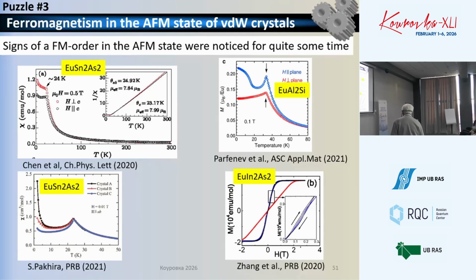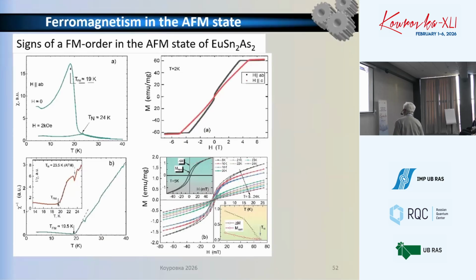So what I want to say is that in all the layered antiferromagnetic materials, you may find signatures of ferromagnetism. To explore this issue, we took a single crystal, and we didn't apply a magnetic field like this, and we see a huge manifestation of ferromagnetic behavior. Of course, when you apply 0.2 Tesla, you immediately wash it out and get what is reported in many papers in the literature. Furthermore, we took precise measurements of the magnetization curve and found, in the tiny vicinity of zero magnetic field, ferromagnetic type hysteresis. It saturates and vanishes. It saturates fully in fields which are much less than the saturation field of the antiferromagnet.